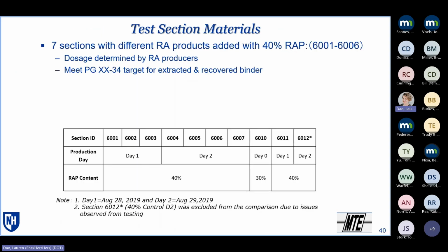Again, as I said, there's 7 different RA products. These were added to 40% RAP mixes. And then dosage was determined by the suppliers. The target was making sure that with that 40% RAP, you met a PG minus 34 target. So those dosages were done, and again, the target was on the extracted and recovered binder.